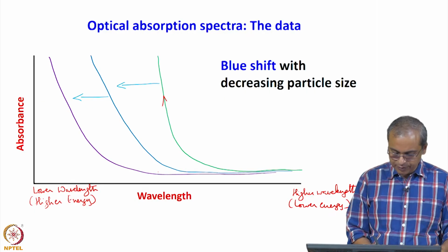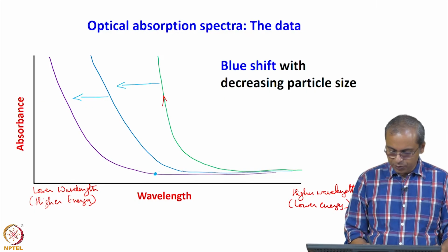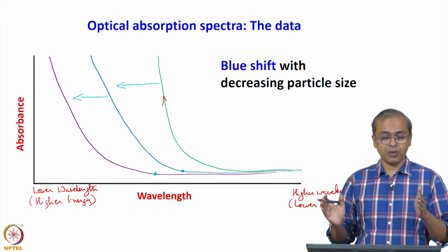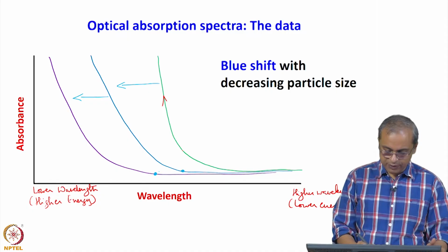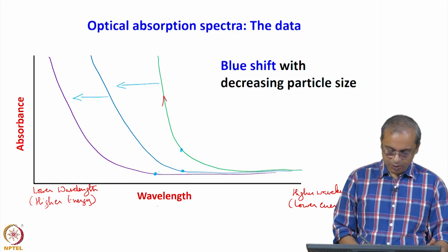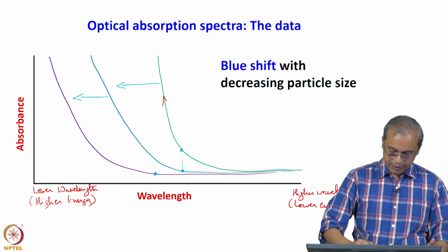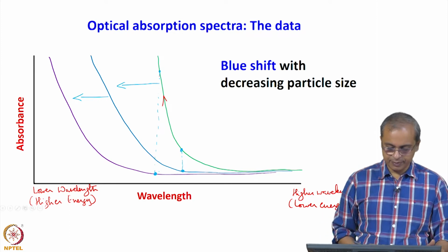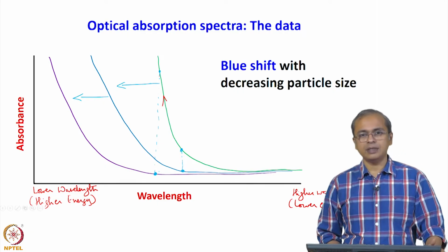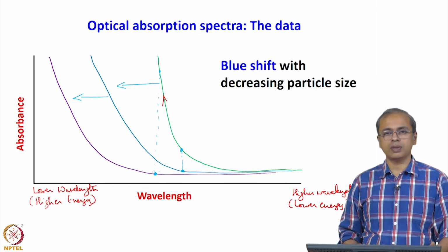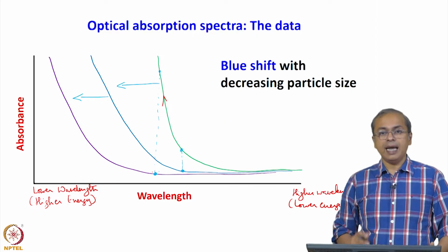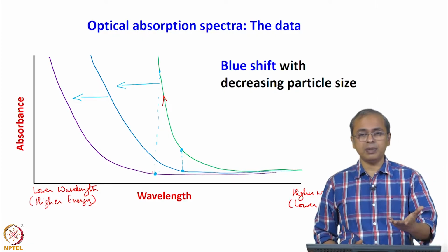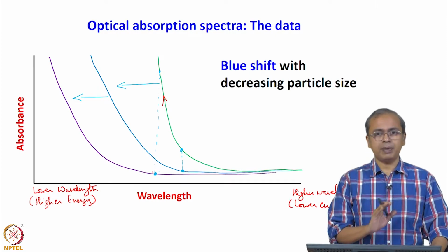because it is able to not respond even when you have now come up to this point and here up to this point, and it is still not showing any absorption. So that means the band gap has changed, because if it were absorbing, already you would have seen this level of absorption, you would have absorbed this much, and here you would have absorbed completely. Look at that, you would have absorbed that much, right. But you are not seeing that; instead it is sitting very close to, almost acting like it is not absorbing, and that means its band gap has changed, and that is something very fundamental to the material. Some fundamental property of that material you have changed simply by going to the nanoscale.